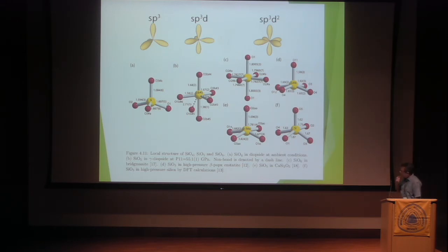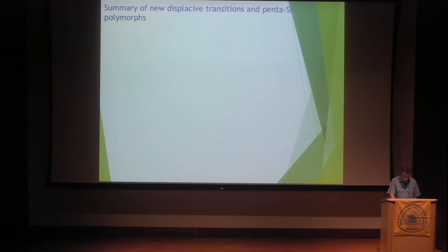So the solid-state chemists who studied the strange coordination states of silicon linked the presence of 5-coordinated silicon with changes in hybridization of silicon orbitals. So you can see that the different geometries, either the square pyramid or the bipyramid coordinations, they have some interpretation in terms of how electronic orbitals are rearranged at high pressure.